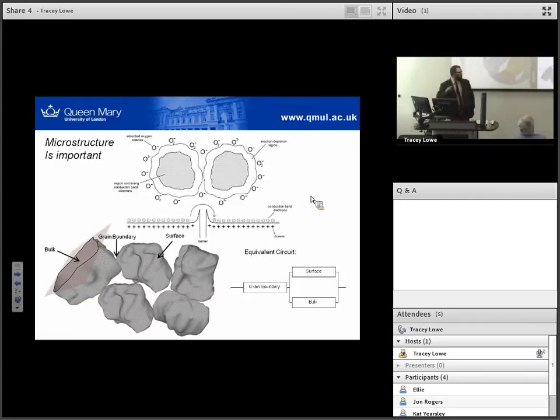Microstructure is super important in this case. Now obviously, if you've got your material like this, you've got three parts: the bulk of the material, the surface of the material where you can absorb oxygen and get these ionized oxygen species. Now these are the parts which are going to react with any analyte gas, and it will only be this surface region which will contribute to the change in resistance or conductivity that you're measuring. Grain boundaries then will merely provide some kind of energy barrier for charge percolation through your network.